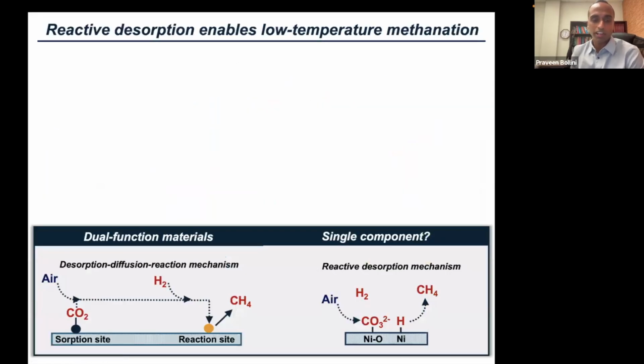The last thing, at least in the carbon capture area, that I'll emphasize again, is that with a new class of materials come new possibilities. Generally, when you're trying to convert CO2 into a chemical product, you're relying on two separate sites where you adsorb CO2, you desorb CO2 at higher temperatures, and then hydrogen and CO2 are transported to your active site where you convert it to a value added chemical. What we're able to do with this class of materials, in fact, is we're able to just bring in air and hydrogen, and without desorbing CO2 at higher temperatures, you're able to reactively convert it to a hydrocarbon, right? So of course, I'm showing the data for methane, which is not a very valuable or useful product to generate, but in principle, this can be done for other molecules like methanol.